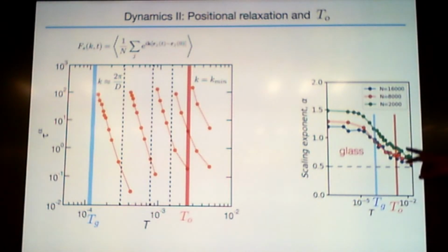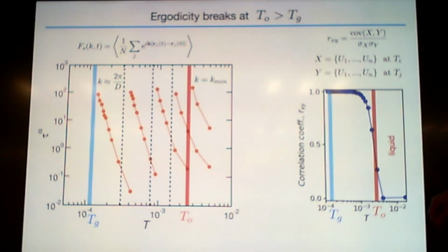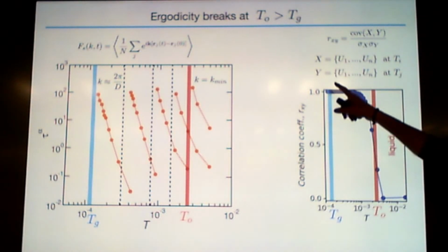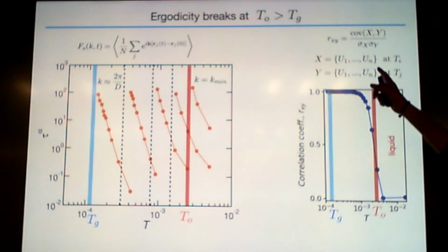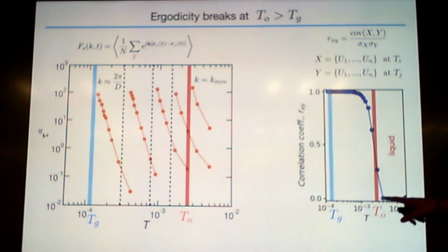Well, the first bar, I'm not going to talk about it much, it's the onset. So what is T0? It's the onset of the supercooled regime, where we measure basically the energy fluctuations. We measure the covariance of the energies at one temperature and correlated with the next temperature, 2 subsequent temperatures. What that means is basically that above T0 they are uncorrelated, so the system can still equilibrate, but once you enter the region below T0, you are entering basically a meta-basin of the landscape. So you get stuck in certain energy minima, and you will never get out of it at finite times. Even swapping particles is not enough. So that's the onset of the supercooled regime.